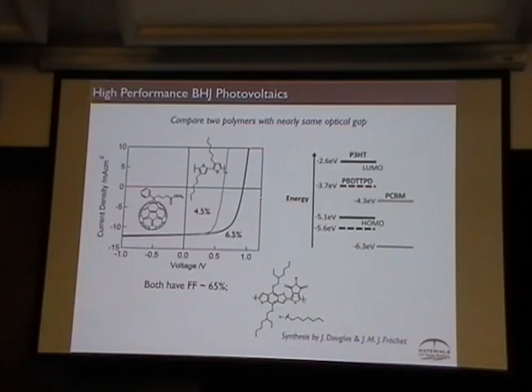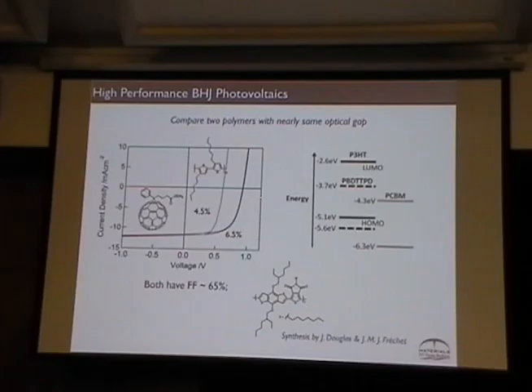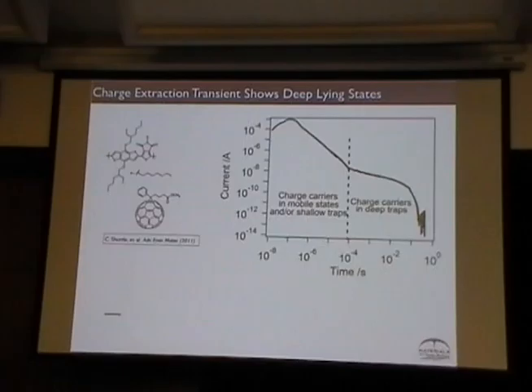The main difference is PBDTTPD has a deeper HOMO at 5.6 eV, while P3HT is about 5.1 eV — about half an eV deeper. These values are from CV done by Fréchet's group with a reference electrode, so you know what they actually are. It's the difference between these two in absolute value that matters.